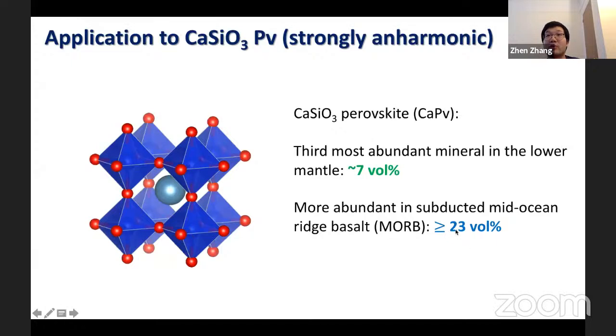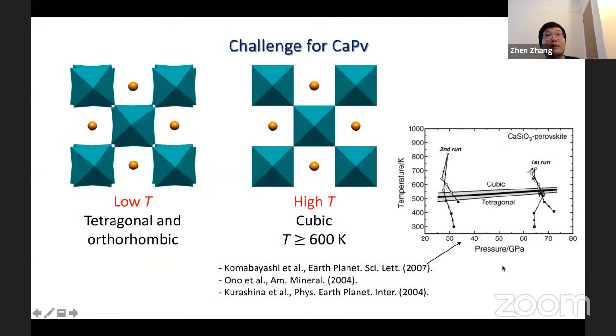Despite its importance, reports of calcium perovskite thermal properties are scarce due to the challenge in dealing with its strong anharmonicity at high temperature and high pressure conditions, for both experiments and computations. It is known that calcium perovskite adopts the cubic phase at lower mantle conditions. It adopts various tetragonal and orthorhombic phases at low temperatures, and it only adopts the cubic phase at high temperatures, for example, temperatures higher than 600 Kelvin at lower mantle pressures. Experimental measurements of cubic calcium perovskite are challenging at high PT conditions.